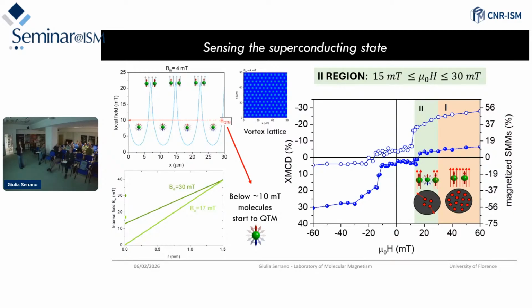We have that locally, close to each vortex, the magnetic field goes below 10 millitesla. So such a low value is already sufficient to make the quantum tunneling of the magnetization of the molecule happen. So in this case, we have a lowering of the signal because some molecules start to perform this quantum tunneling of the magnetization. This is a sketch of the vortex lattice, which will be less and less dense the lower the magnetic field is. So we arrive at a certain point that is roughly 15 millitesla.